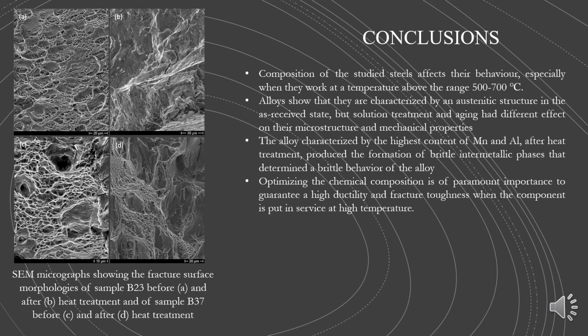Also, the alloys characterized by high content of aluminum and manganese produce, after heat treatment, the formation of brittle intermetallic phases that determine the brittle behavior of the alloy. Hence, it can be said that optimizing the chemical composition is of paramount importance to guarantee a high ductility and fracture toughness when the component is put into service at high temperature.